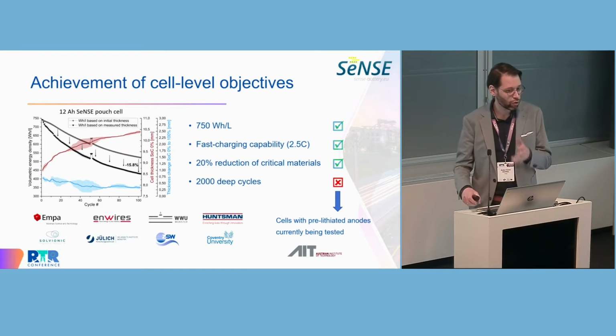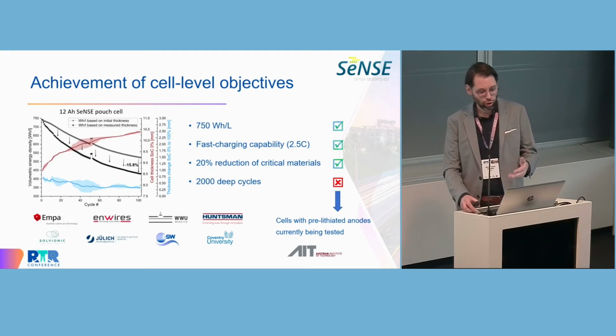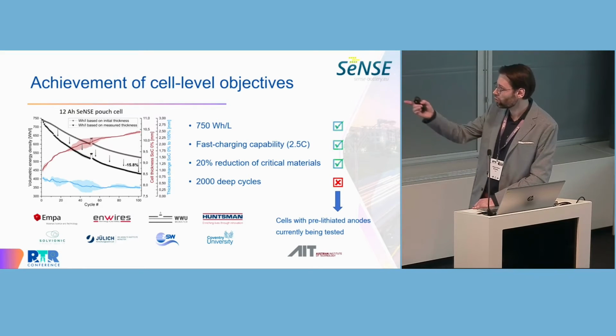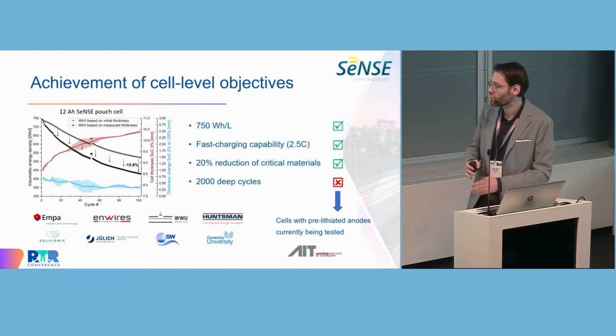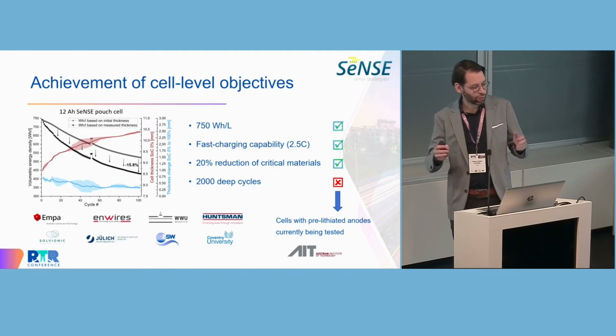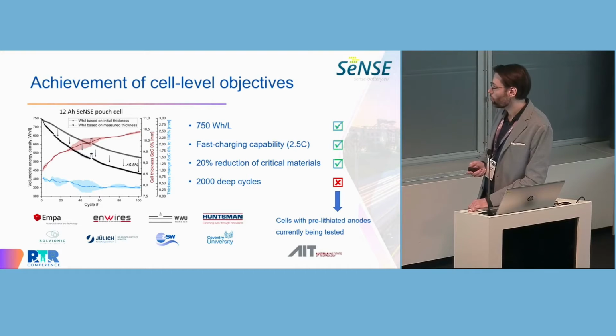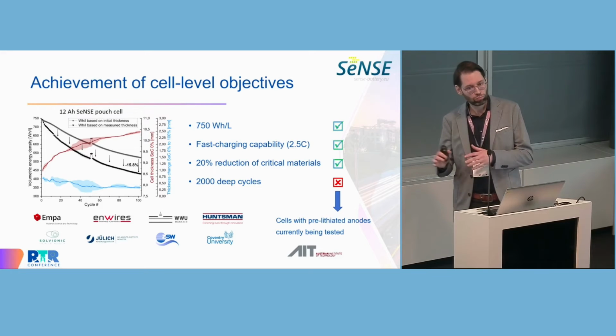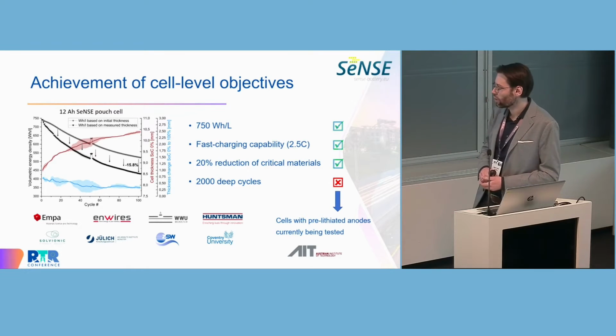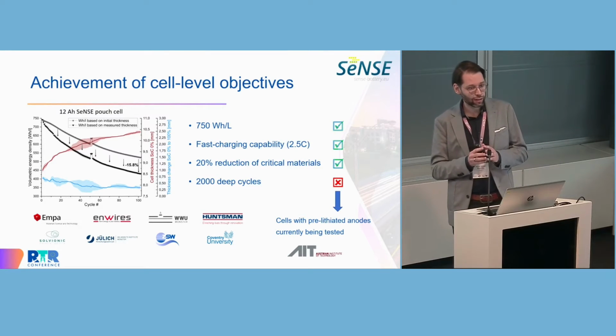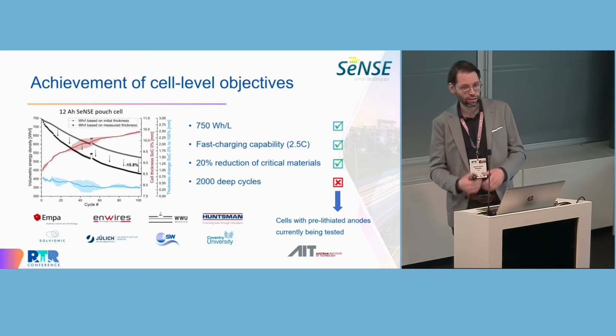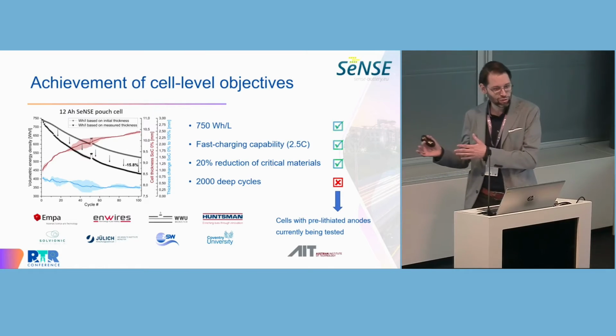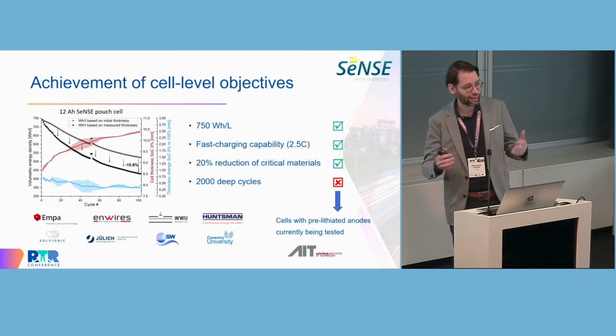I mean, with this pre-lithiation approach that I introduced before, we actually managed to improve the cycling stability compared to what I'm showing you here, but we are still, of course, a bit away from the 2000 cycles. But we managed to demonstrate all the other technologies also in nickel-rich NMC graphite cells, so including the aqueous processing and so on. And those cells, the first generation cells, they're still running, and they now reached 1,500 cycles, and they're still above 80% of the initial capacity, but it really also takes a long time to demonstrate 2,000 cycles if you don't want to go to a really high rate, right?